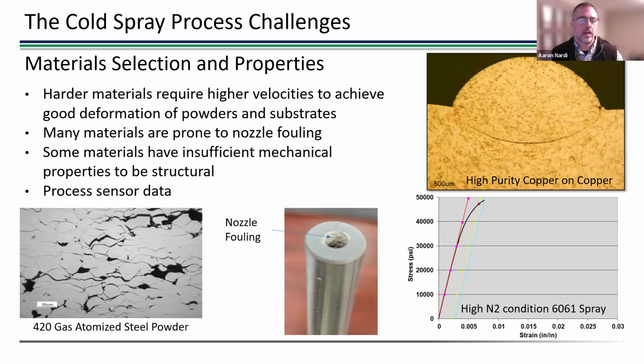And then the last thing I'll leave you with as far as challenges go is more of the material selection and properties aspect. So generally speaking, a powder that's softer, a powder that is not significantly hard, sprays better. So you see here an example of 420 stainless steel that's been gas atomized. In the gas atomized condition, this has untempered martensite. It's very brittle, very, very high hardness, and it doesn't really deform well and bond well.